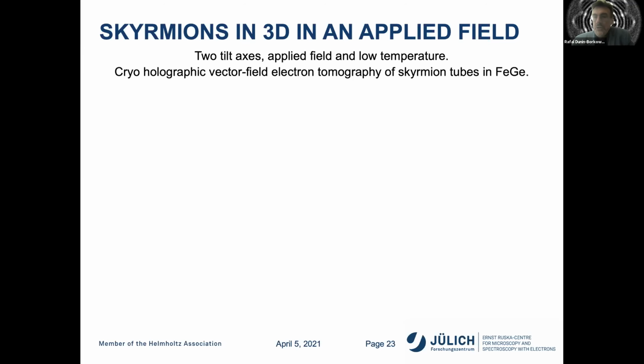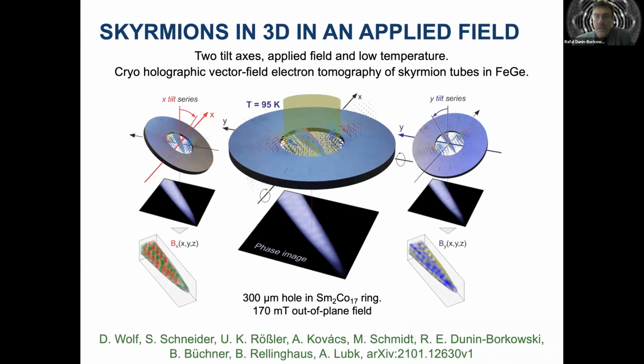So here I'd like to show some recent work which has been carried out by the group of Axel Lubk with Sebastian Schneider, Bernd Rellinghaus together with us. And here he overcame some of these problems by a very clever method, which involves making a ring, 300 micron with a 300 micron hole in it, of a hard magnet, samarium cobalt, which is magnetized perpendicular to the plane, and then inserting a needle-shaped sample of iron germanium into this ring. This ring can then be cooled. The stray field of the ring exerts an external magnetic field on the needle-shaped sample, and that needle-shaped sample can then be tilted about 2 directions in the presence of an applied field at low temperature.